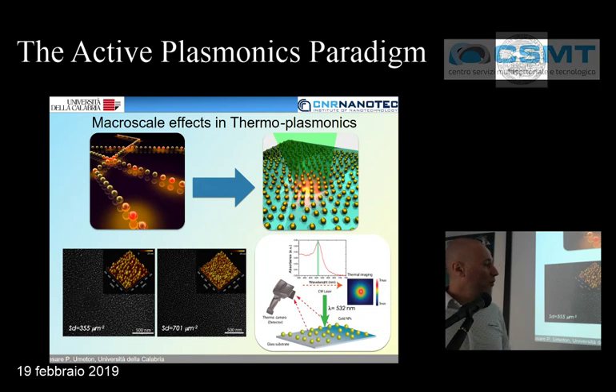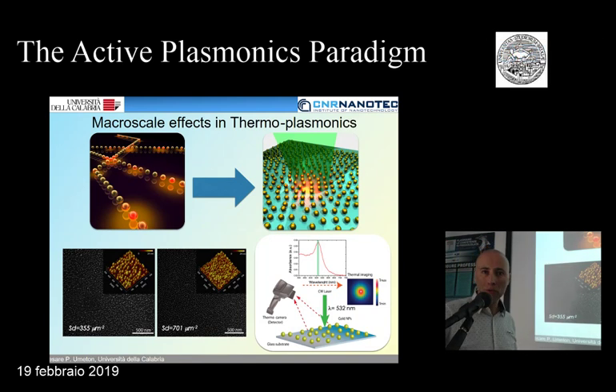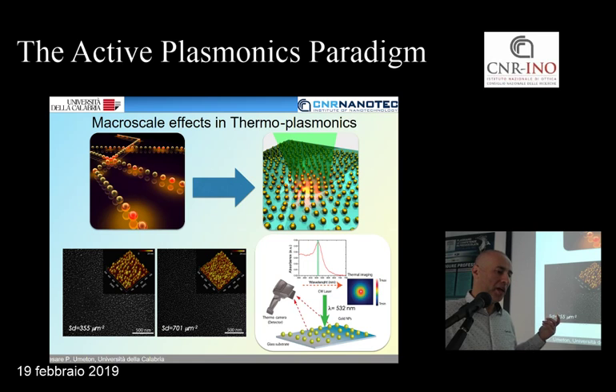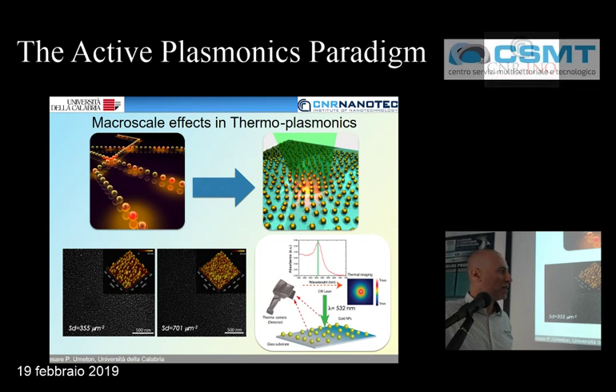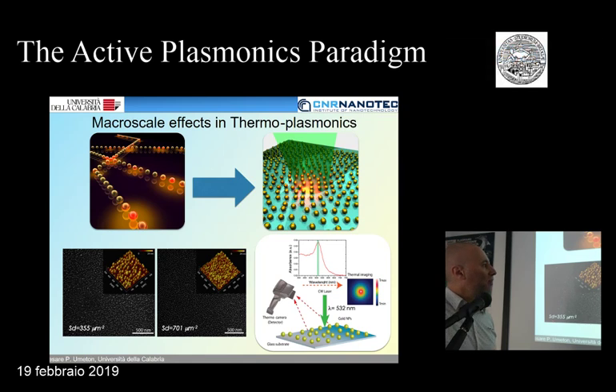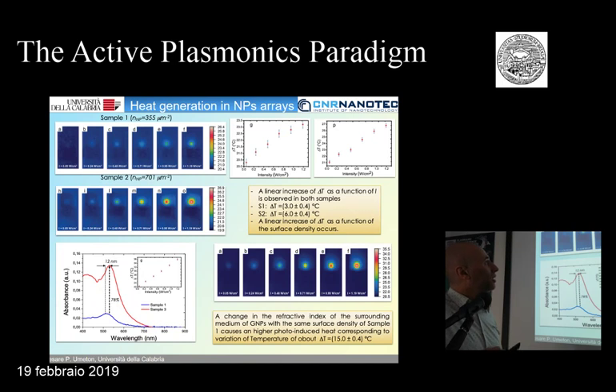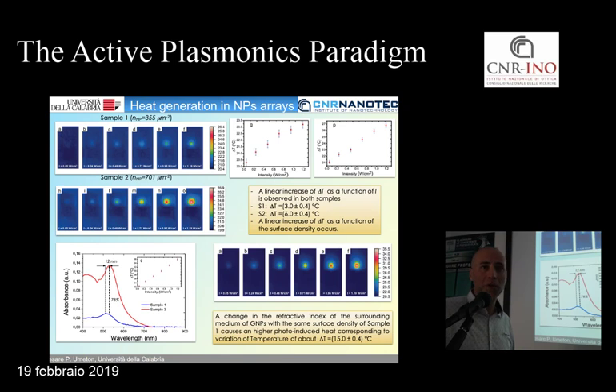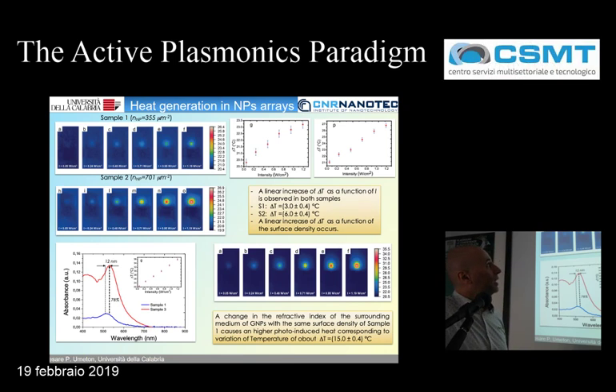So, what really happens on the nanoscale when you consider different distributions of nanoparticles? As I said, the thermal effect is a collective effect. So if you increase the density of particles, you can have a different thermal behavior. So this is what we did, and by changing from one density of particles to another, you have different behaviors in the thermal response of the system. Here, for example, we have the intensity of pumping, and on the vertical axis we have the change of temperature with respect to the room temperature. So as we can see, this depends on the density of the particles.